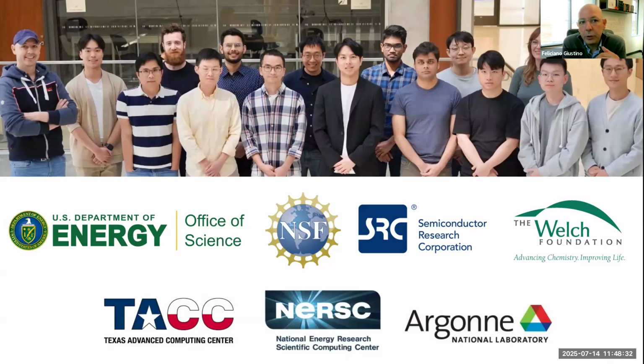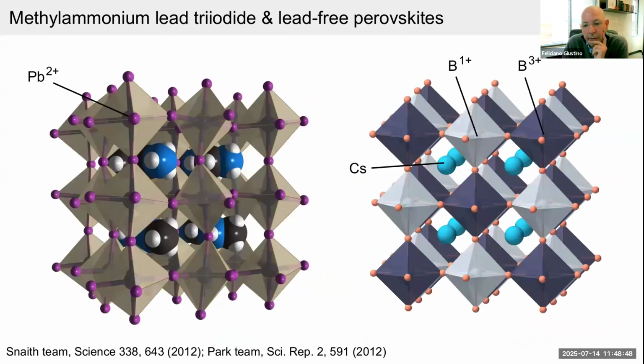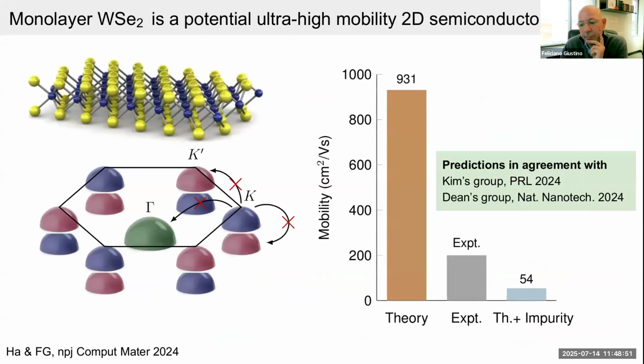So while graphene is not being used directly in the channel, I think it will probably become more and more popular as an outer layer in order to help improve the mobility of these devices. In fact, I don't have slides about those experiments, but in this paper last year in Nature Nanotechnology by Dean at Columbia, they actually used a thin graphite layer on top of this stack in order to further improve the mobility. So that's an interesting direction moving forward.